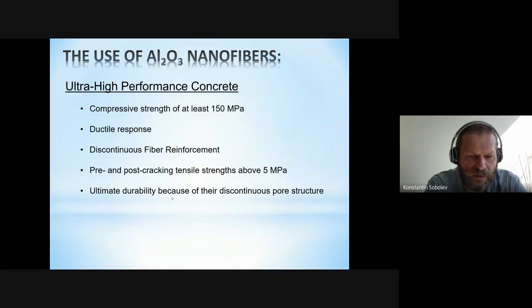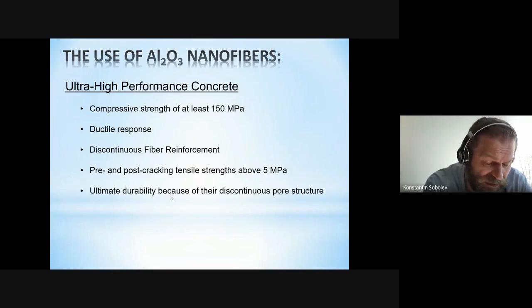Let's discuss other products which we tested. Nano alumina nanofibers, and we use this for ultra high performance concrete, which usually would require compressive strengths of at least 150 MPa. There were different definitions, but the one I have here is adopted by the American Concrete Institute. It should have ductile response, which is realized with discontinuous fiber reinforcement. An important parameter is pre and post cracking tensile strengths of more than 5 megapascal. And obviously, it is considered to have ultimate durability because of this discontinuous pore structure.